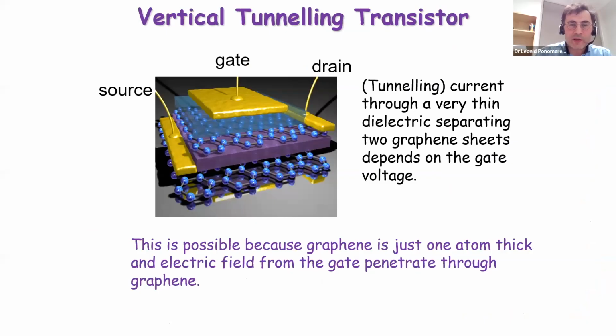Right, so what about transistors? I told you that there is a way around, and indeed, we can make graphene field effect transistors with a high on-off ratio. I'm really glad that I was the person who proposed this idea, and it turns out that it works. Instead of making a planar device, not using graphene just as a conducting channel, we make a vertical device. We take two graphene layers, one of them drain and the other source, separated by a thin insulator, for example boron nitride. If this insulator is very, very thin, it works as a tunneling barrier. Current can flow through it, but the current is quite small.